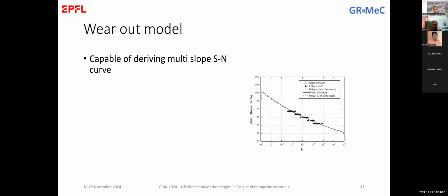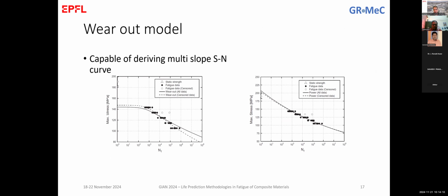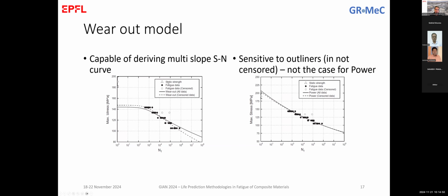So the wear-out model is the model you remember, the model of Sendeckyj, that helps to produce curves that are not only based on the power law for the entire lifetime. So they allow to have sigmoidal curves with multiple slopes, and this helps in certain cases to consider also the static strength, and improves a lot the prediction. What is important in this case where we have this model is to be careful with outliers, the points that we discussed before that are not following the trend.